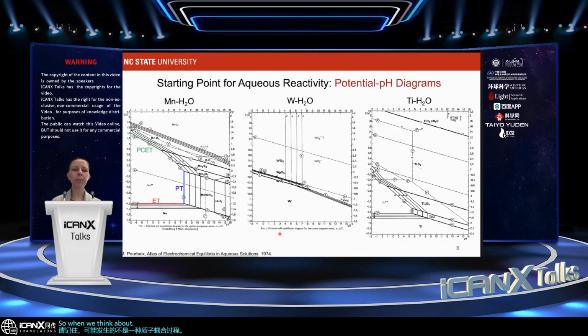So when we think about metal oxides for energy storage and conversion reactions in aqueous electrolytes, the starting point is really to understand something about their stability, and that comes from the potential-pH diagrams, or the Pourbaix diagrams. And that will readily help to identify metal oxides that we would expect to remain as stable solids at our pH of interest. So here I've just pulled out the potential-pH diagrams for manganese, tungsten, and titanium. These are essentially phase diagrams between water and the transition metal.